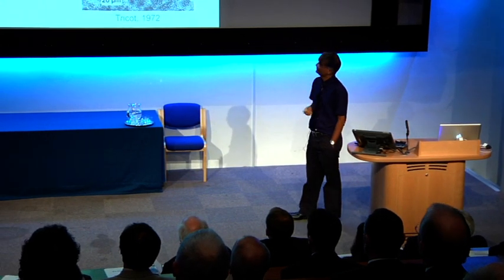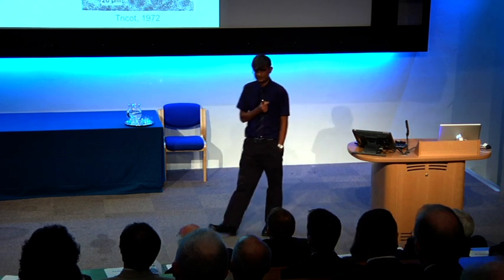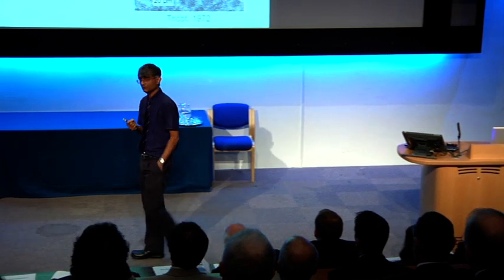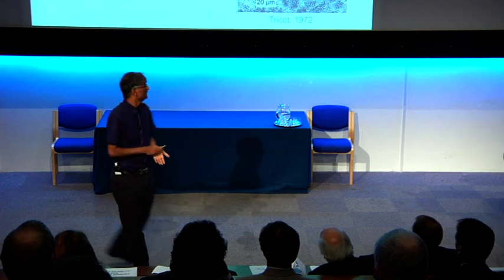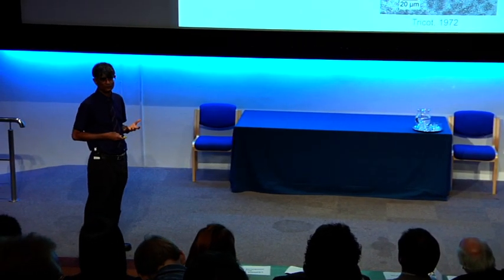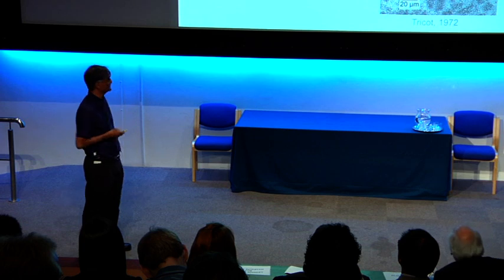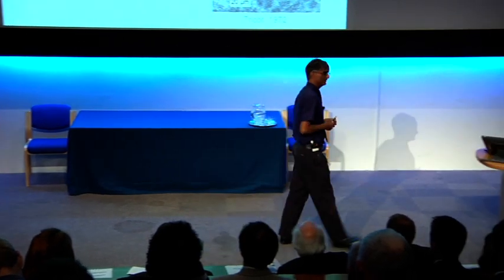Now, what can we do about this? We don't know the consequences of hydrogen. We don't know whether hydrogen actually contributes to the initiation of cracks. Now, the initiation of cracks is very important because under pulsating stress, the crack faces will rub against each other, and that will create something called white matter. So, a lot of the papers will assume that white matter is what causes damage, but we don't know that. Is it the actual initiation of the original defect which leads to white matter which then causes difficulties? Okay, let's put all that aside and let's think about what we can do about the hydrogen problem.